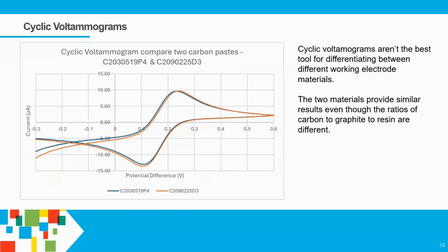Also, this is another example of cyclic voltammetry. So these two inks have very different compositions. They have the same materials, but the ratios between the carbon, the graphite, and the resin are completely different. But from the cyclic voltammogram, you can't really tell much.